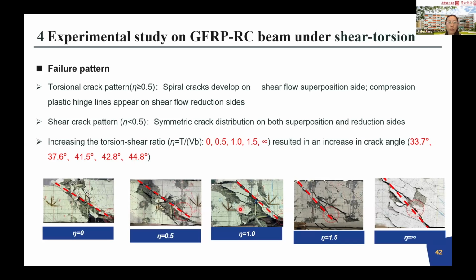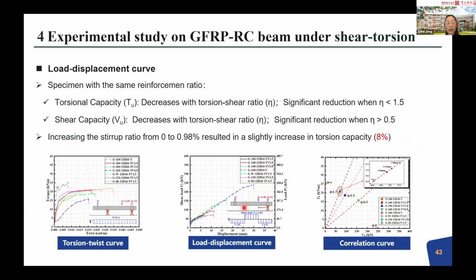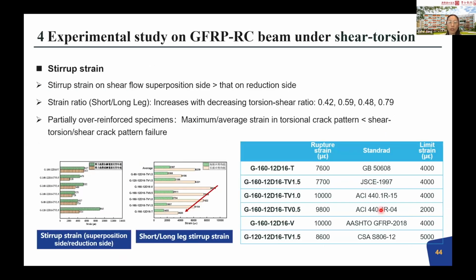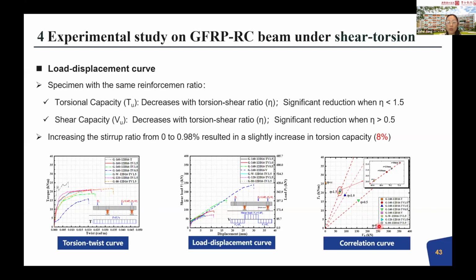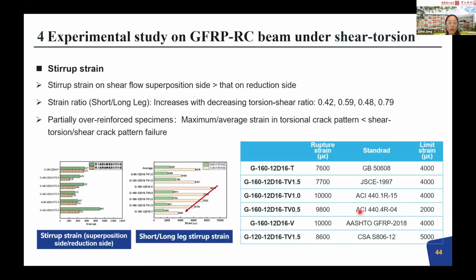And further, we're finding the behavior of torsion and also the shear behavior, and the most important is the interaction curve. Here is the interaction curve from pure torsion to pure shear, which is along this behavior. And later I will show how it correlates to the steel interaction curve. And also for the stirrup strain, we find that when the shear force increases, the long leg strain will increase a lot. That is very consistent with the resisting mechanism in shear and in torsion.